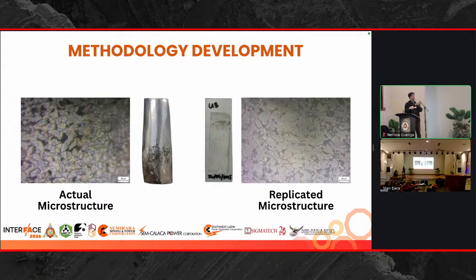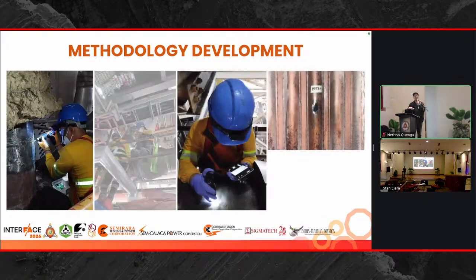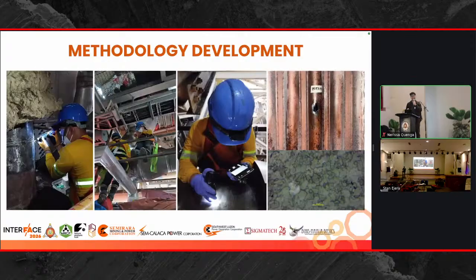By our testing and experimentation, we were able to produce quality replicas that accurately replicate the microstructure that we need for subsequent failure analysis. So after practicing and perfecting our methodologies, we were then able to apply it in our fieldwork activities, as you can see here. We are literally fighting for our lives, though we are, of course, employing safe protocols and proper PPEs for this. But as you can see, we are literally on the tubes, on scaffoldings, just to get the microstructure of the actual part without breaking the actual part needed.